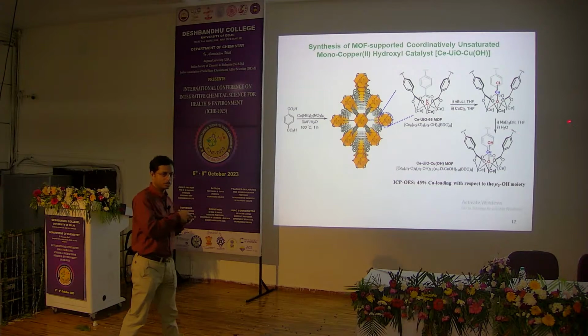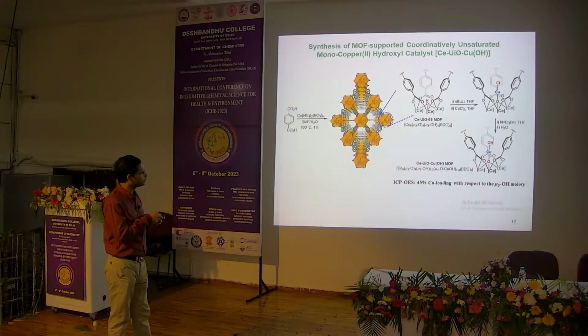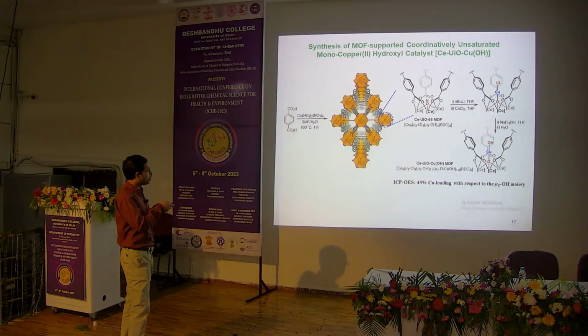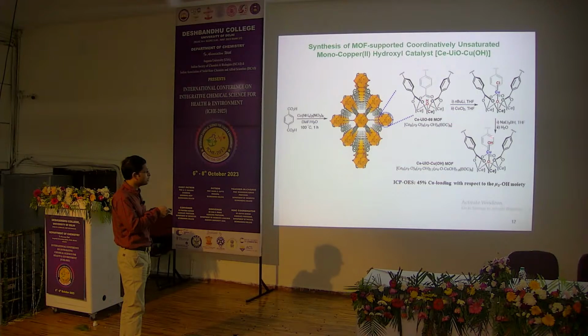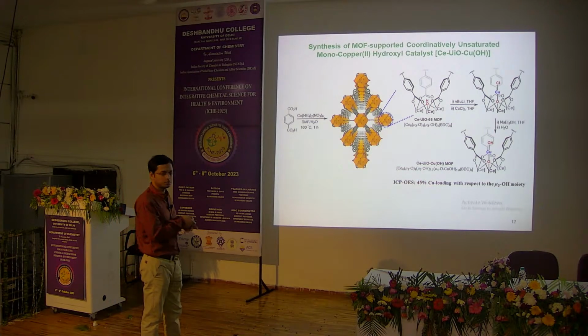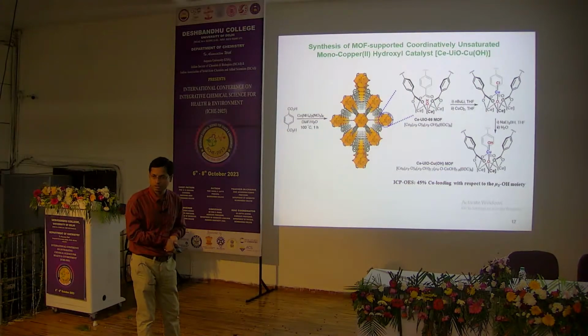And next we treated with sodium triethylborohydride. This sodium triethylborohydride converts the copper chloride to copper hydride, and then we added water to get this copper hydroxyl species. Not all hydroxyl groups are metallated with copper. ICP-OES tells us that about 45% of the OH groups are metallated with copper.